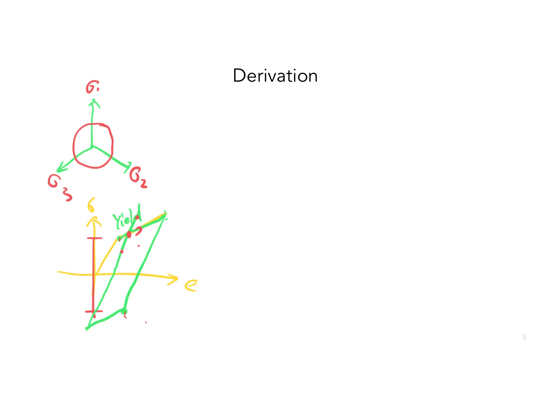So why is that? Now let's look at it on the pi plane. In perfect plasticity, the J2 von Mises yield criterion would be fixed. In the case where hardening or softening occurs, each time I reload the material, it may have a new yield surface. That new yield surface, we actually don't know how it would look.